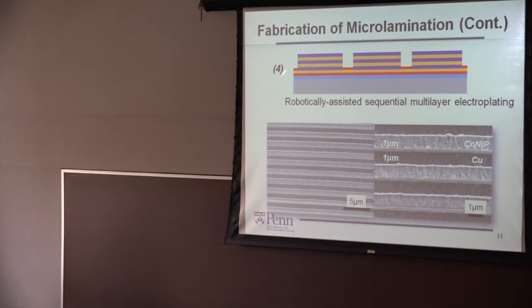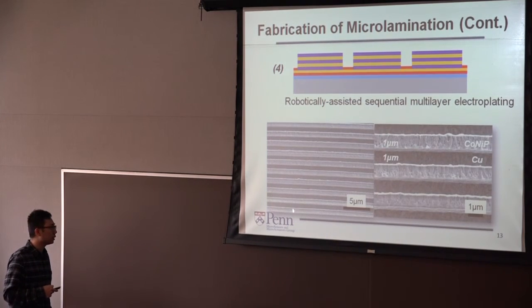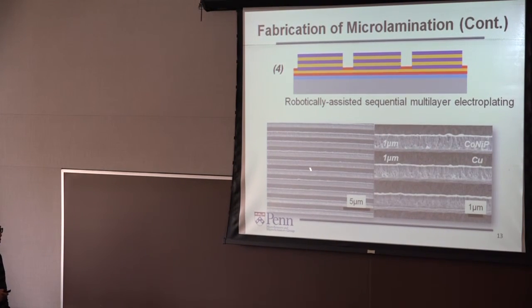All right, so after electroplating, you remove the mold, and you basically inspect your cross-sectional image in SEM. And here we show a 10 pair laminated magnet, and this is an enlarged view. So we do a selective copper wet etch so as to give you the contrast. This white protruding layer is cobalt nickel phosphide, and the receding layer, because it's etched, is copper.